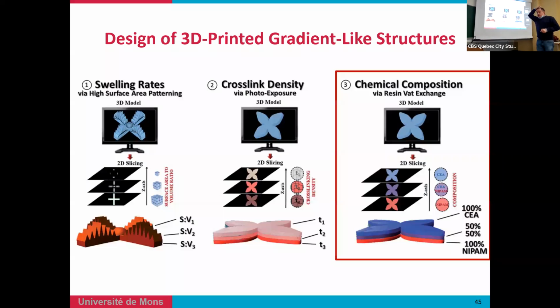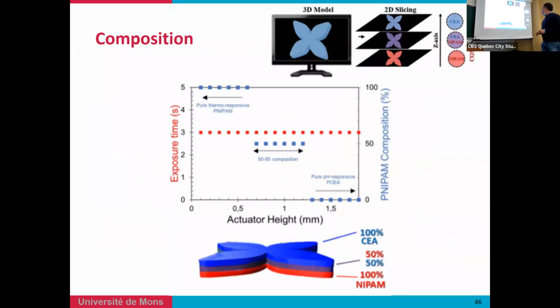As a last example in the case of actuators, we play with the chemical composition. Here, we combined the polymer related to the LCST with the second monomer I mentioned, the acrylic monomer that is sensitive to pH. We construct this actuator based on 3 layers: 100% polymer, an intermediate composition, and 100% of this acrylic acid comonomer.